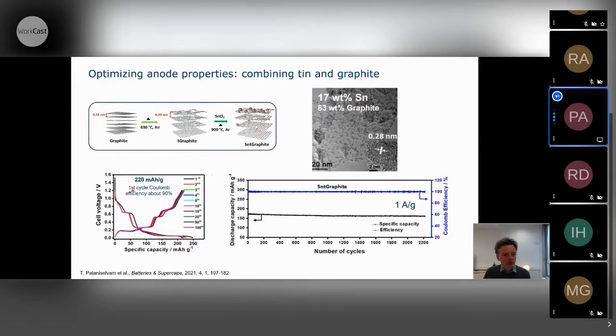And this value, the first cycle Coulomb efficiency, is really important for application. Many materials that perform well sometimes have very low values, maybe 50% or so. And this means you cannot use them in a real battery. So this first cycle efficiency should also be as high as possible, and 90%, I think, is quite a reasonable value. If you do long-term testing over 2000 cycles, and here we went to a higher rate, simply because otherwise the test would last very long, you can still see the material has a very stable capacity, and there's only a minor decay over so many cycles.